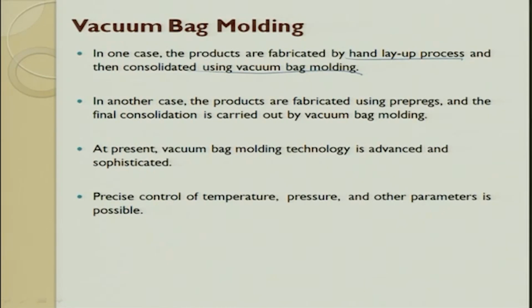See, what happens in hand layup processes, we always have a restriction in the reinforcement. If you are really a very good, efficient, skilled person for making this hand layup process, you can touch up to 60-65% volume fraction very easily. Normally we go around 30%. So, if you want to make 60 or 65 or 70% with the hand layup process, and if you are not pretty sure about the quality, it is better we do vacuum bagging and we enhance it.